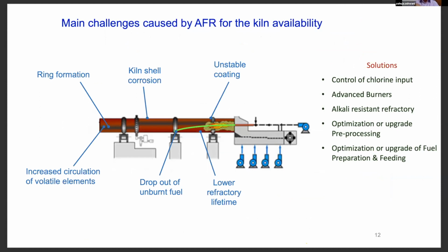While people feel that RDF, because it has a calorific value, is a direct coal replacement, it is actually not true. There are a lot of challenges when we try to use alternate fuels in the rotary kiln main burner as well as in the calciner. There are lots of process problems like ring formation, leading to kiln shell corrosion, unstable coating, increased circulation of various volatile elements and chlorides, dropping of unburnt fuels in the kiln leading to process problems, lower refractory lifetime, etc. And also an increase in the heat consumption of the rotary kilns.